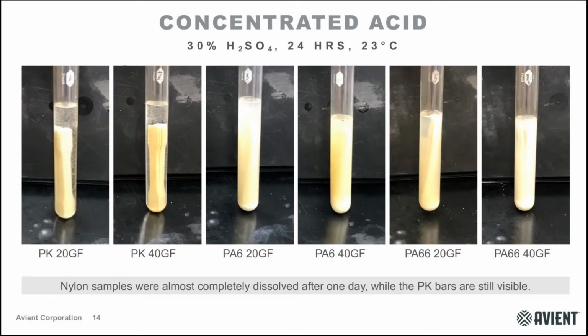And one of the great benefits of using polyketone is its enhanced chemical resistance compared to nylons. This is seen in this slide demonstrated against 30% sulfuric acid. And we're just taking tensile bars and dropping them in and doing some simple soak tests. Now, glass-filled nylon 6 and 6,6 test bars dissolved within 1 day of this experiment, while the polyketone samples remained stable after 20 days. These images really show you a stark visual representation of the excellent chemical resistance of polyketone.